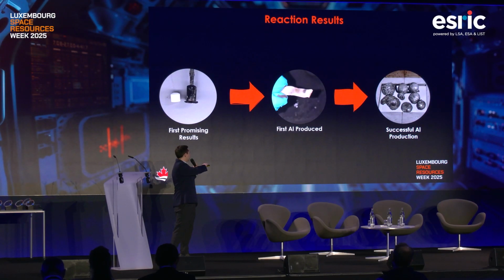So then we kept improving our process, kept improving the electrolytes, the electrodes, the different variables in the electrolysis. And the second picture shows the first actual aluminum particles that were detached from the pellet. You can see that there's a finger over there. Just as a comparison, it shows that the spherules were very, very small. And then the last picture shows successful aluminum production. That's after standardizing the process, we were able to actually produce better spherules.